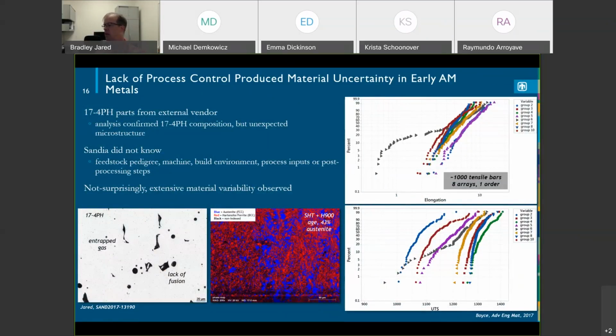And this is basically 8 different tensile arrays, roughly 1,000 parts, and we see a very large variation in these, and it's very concerning, right? So you see microstructure variation, you see porosity variation, and really this was not very comforting as we looked at material uncertainty of some of these materials, and so it raised a lot of questions. And I'll show a slide later that shows sort of what we've done to make improvements on this.